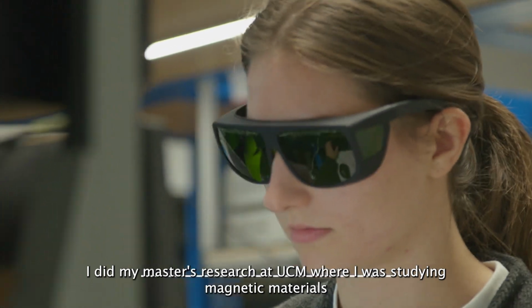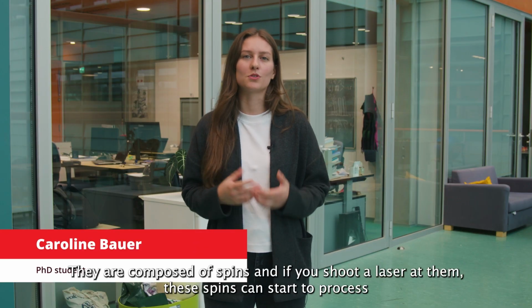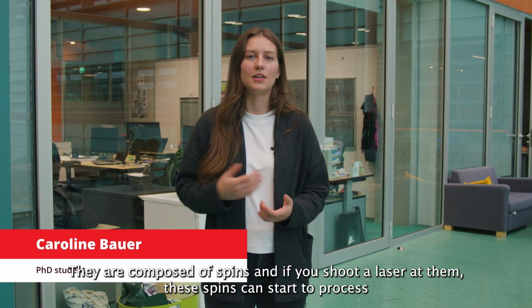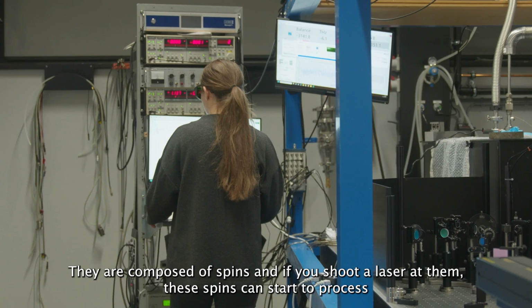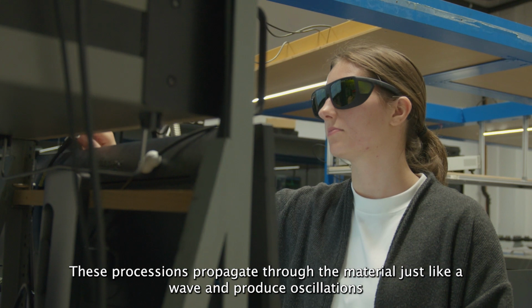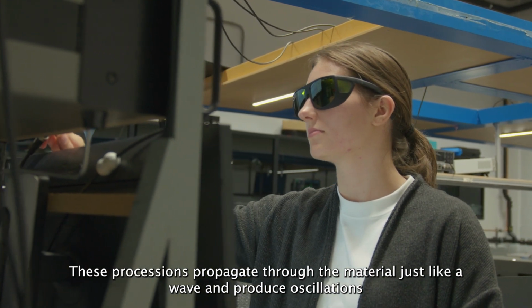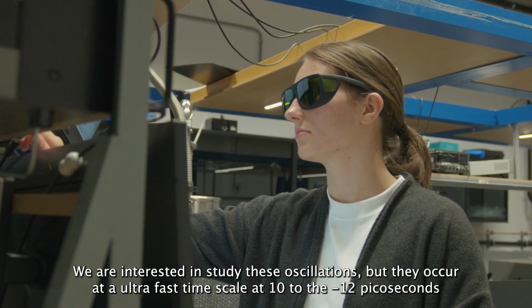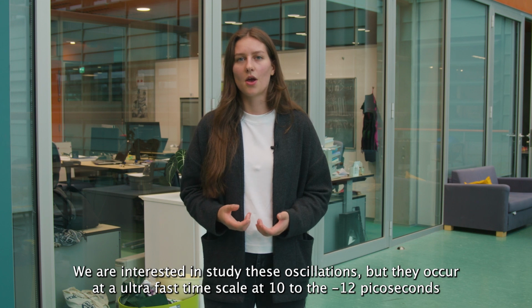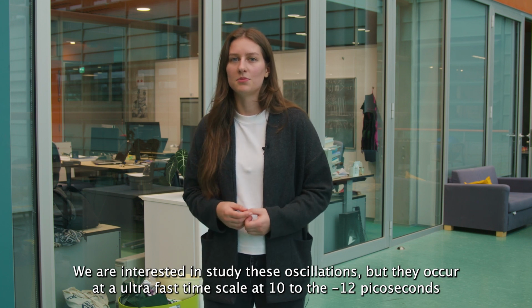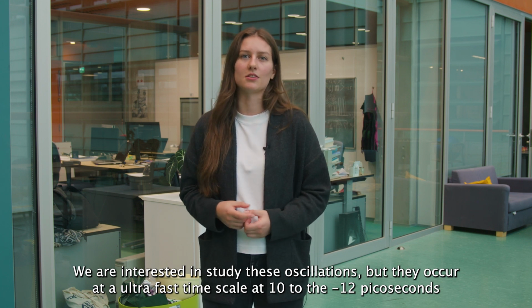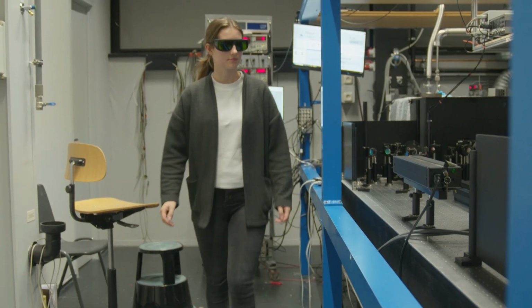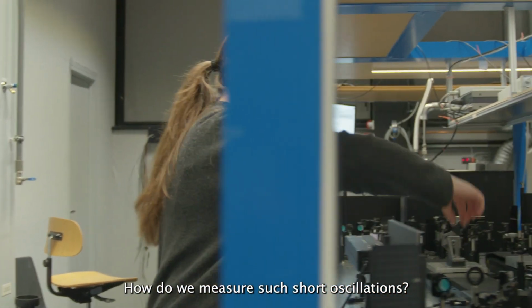I did my master's research at UCM, where I was studying magnetic materials. They are composed of spins, and if you shoot a laser at them, these spins can start to precess. These precessions propagate through the material just like a wave and produce oscillations. We are interested in studying these oscillations, but they occur at an ultra-fast timescale, 10 to the minus 12 seconds, picoseconds. But how do we measure such short oscillations?